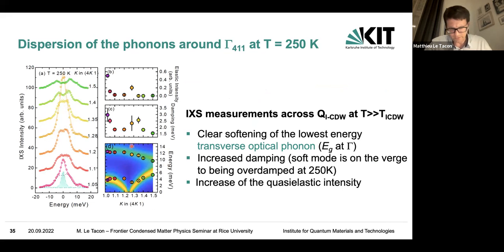We can extract from that the dispersion of two modes. Sorry, the contour plot here is the calculated intensity for the soft phonon, the structure factor calculation. I'm not entering the details of the fitting procedure, but basically we can constrain it quite severely so that we're capable of distinguishing what is really the elastic contribution and the phonon contribution to this fitting.